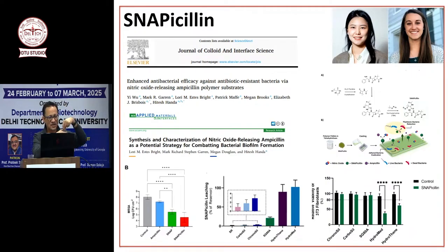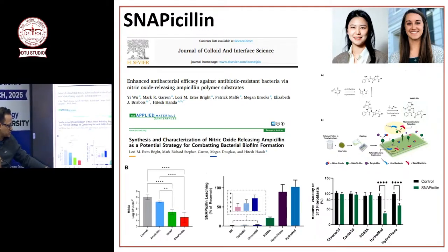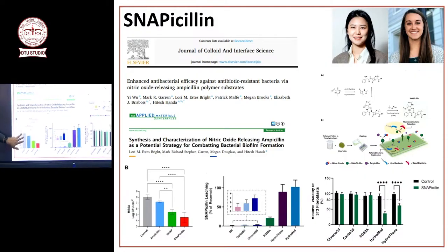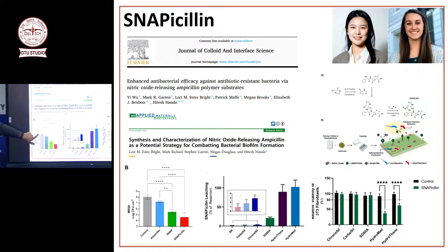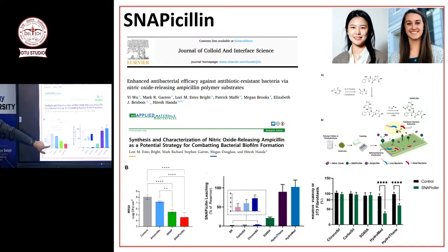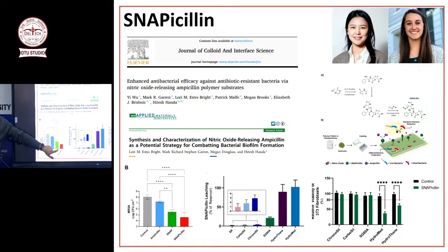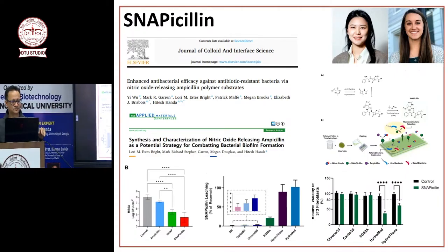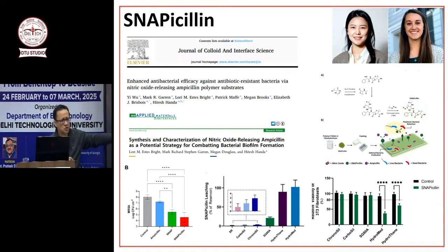Okay. So you have a biofilm and NO will go inside the biofilm, disperse it, and now antibiotic and NO both can kill it. But by itself, antibiotic cannot kill a biofilm. And here is that data. What we did is we grew MRSA on different surfaces, on a polymer surface, let's say. And then we exposed it to ampicillin solution. First of all, we looked at MRSA and we homogenized it on a catheter and we saw this much bacteria was there. Other surface we exposed to ampicillin solution for whatever time, I don't remember. And then we homogenized it and we saw so much bacteria was there. We exposed it to SNAP solution, and when we exposed it to snapicillin solution, it took care of bacteria better than anything else.